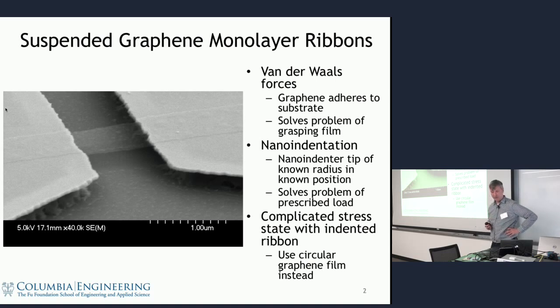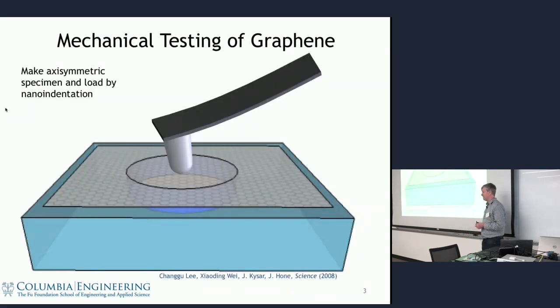And there were a few other groups that had started doing mechanical testing of graphene in this kind of configuration, where you push on the middle here, and you see how this ribbon, very wide ribbon, but the suspended membrane deflects. And this is very nice, but it has some problems, right? Once you indent this, you actually have a complicated stress state, and you also have issues with clamping and edges. So as soon as you have a small defect at the edge, you tear, and you're not seeing the intrinsic properties of the graphene. Right? So what we set out to do, this is now ancient history, so this is our paper from 2008.